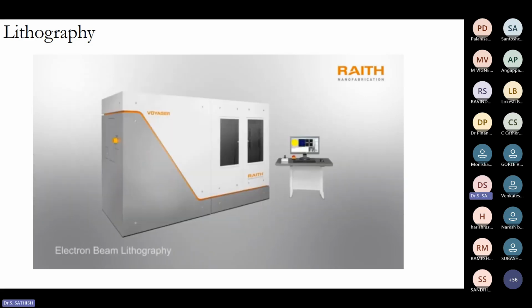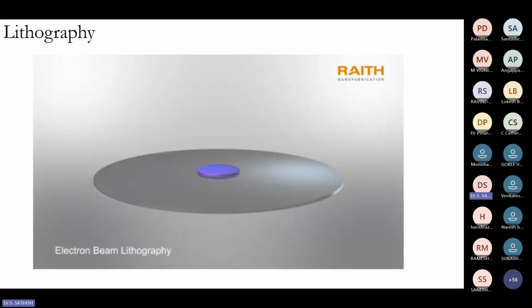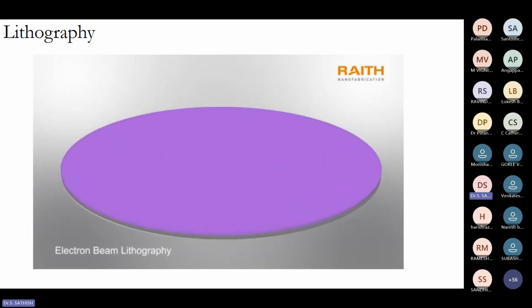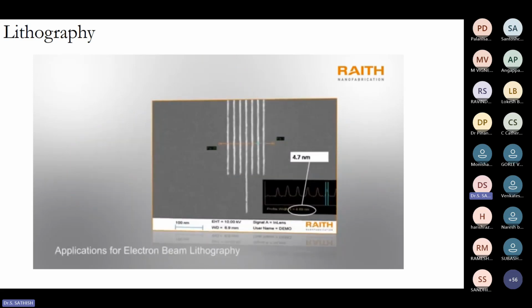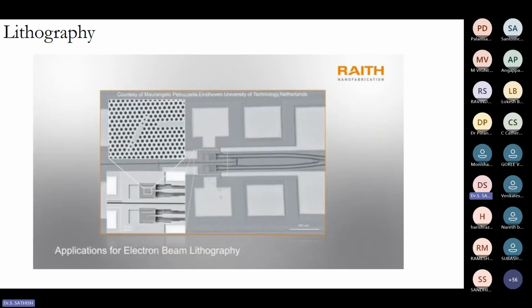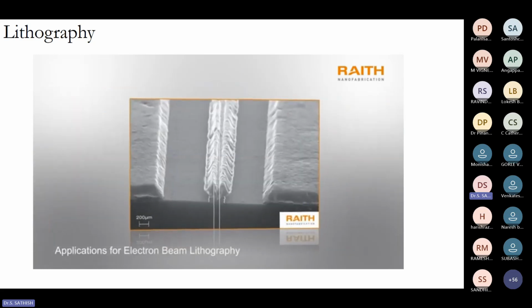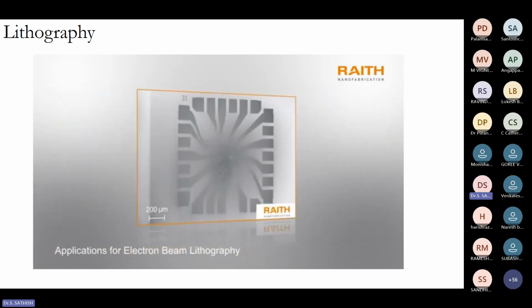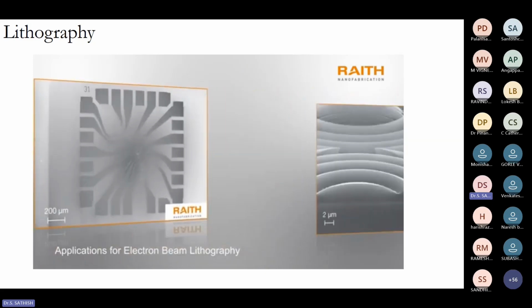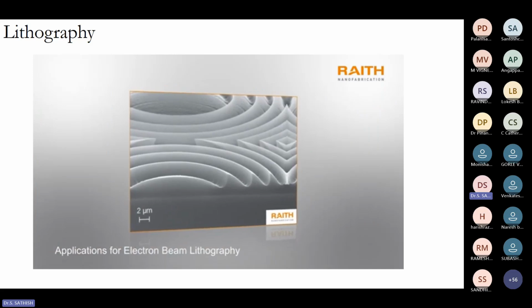Electron beam lithography uses the same process scheme, but a focused electron beam is used for exposure. The beam is accurately directed to positions on the wafer to form the pattern. The electron beam exposes the pattern dot by dot and line by line, which can be more time-consuming than photolithography. However, it is a more flexible system and does not require expensive masks. The focused electron beam also allows feature sizes below 10 nanometers to be generated. Common applications for EBL are rapid prototyping and small batch production, where electron beam lithography and photolithography are used in conjunction, as well as the fabrication of masks and imprint templates.